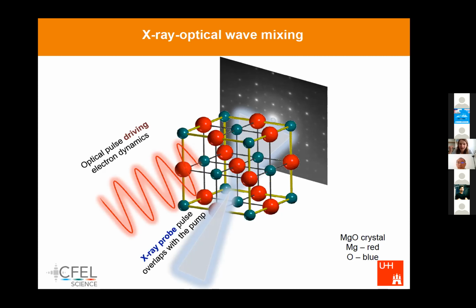Here I'm going to show you the process that we propose. It is called X-ray optical wave mixing. We have an optical pulse which acts on a crystal and induces electron dynamics in this crystal. So the crystal is laser dressed, and while the driving pulse drives dynamics in the crystal, we propose to image it with an X-ray probe pulse that simultaneously shines on the crystal. The idea is that X-rays have a very short wavelength, which gives access to the atomic scale.